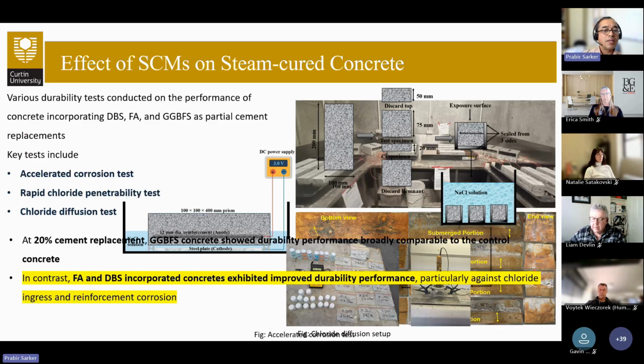Some of the tests we've done are accelerated corrosion test, rapid chloride permeability test, and chloride diffusion test to see the effect of these SCMs on the steam cured concrete commonly used for precast concrete like culverts. This shows some of the photos, and this is the chloride diffusion test setup.